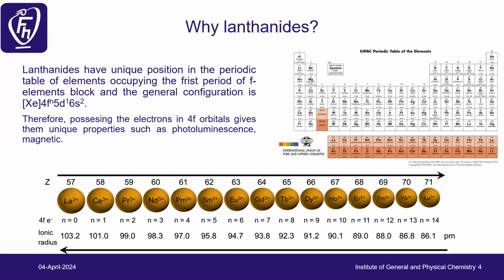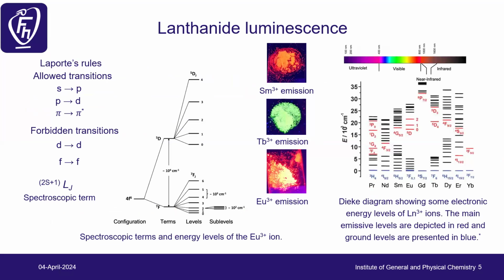Also, because of their chemical properties, which differ by just one electron, they are difficult to extract and refine, and that's why we also call them rare earths, because they are difficult to process when extracted. The lanthanide luminescence comes from the Laporte rules, which give allowed, partially forbidden and forbidden transitions. In lanthanides, the 4f to 4f transition is forbidden, which can be slightly relaxed when we introduce them in the crystal field or ligand field of